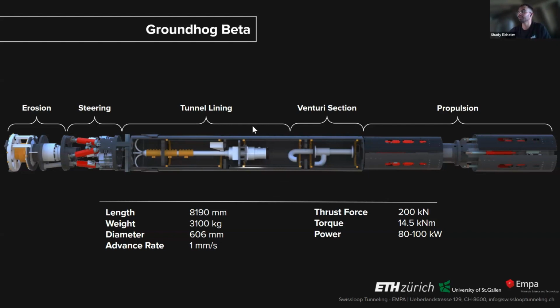Then the tunnel lining section, which was also the reason for the Innovation Award. We melt the polymer in this white rod, which is on a commercial extruder, and the polymer is then extruded to the outer wall of the machine, such that a tunnel is created. The Venturi section is responsible to basically suck the soil that was conditioned from the erosion and then to bring it back outside of the tunnel. And finally, we have the propulsion system. It basically clamps against the tunnel wall and then pushes the machine forward. And we have two sets of plates in order to have a continuous advancement.